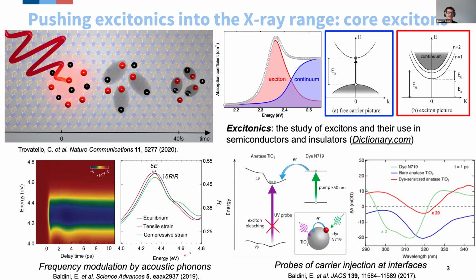So the one on the left is working on titanium dioxide anatase. It's a pump-probe experiment. Anatase also has excitons. And what you see here in this pump-probe are these oscillations. These oscillations are due to an acoustic wave traveling in titanium dioxide. And as it propagates, it's modulating both the probability of absorption of an exciton and also its frequency.